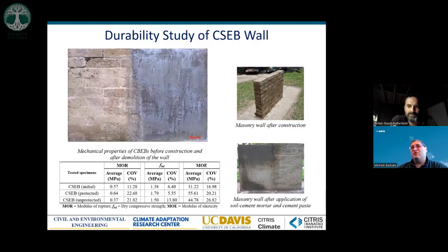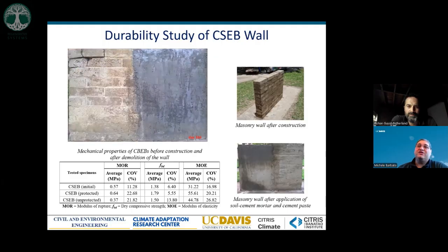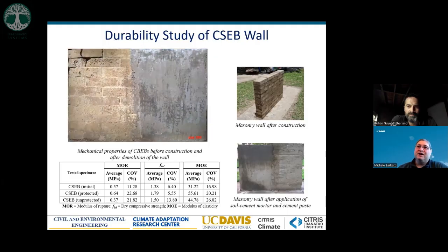The additional thing we did was to cover half of the wall with a soil cement mix with similar composition as the material that we used for the blocks. And then we looked at what was happening on the two different sides of the wall. Now you can see in the short video that I showed you how the left side of the wall, the one that was left